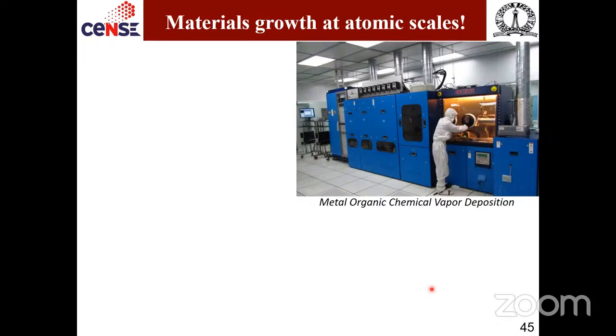So at IISc, we did it using this reactor. This is called metal organic chemical vapor deposition. It's ironic that the films we are growing are a few nanometers in thickness, which is a very small number. But to have a controlled deposition and to control the defects in these materials at the parts per million range, you need a reactor which is as big as this. This reactor would cost about 10 crores of rupees, and the maintenance of such reactors is about 1 crore rupees a year.